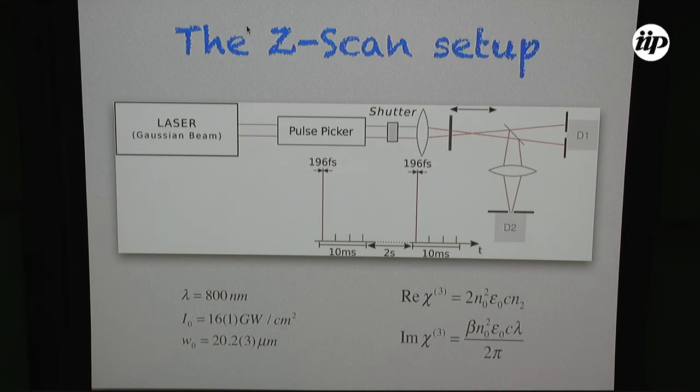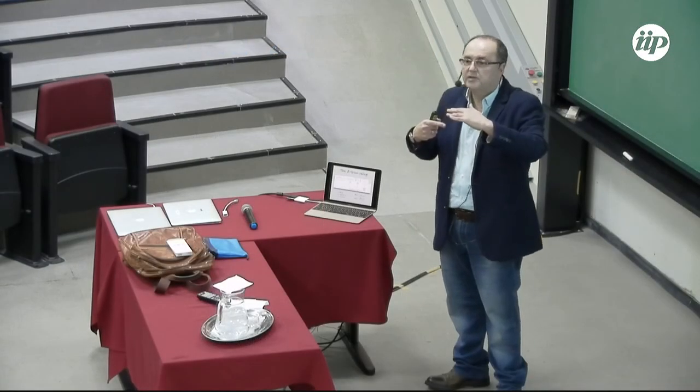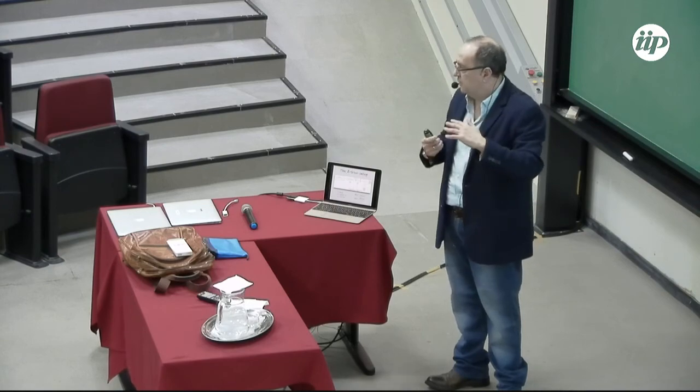You may ask, for example, why do you put this shutter here and you don't work with these small pulses from 0 to about 2 seconds? The response is that if you take into account these small amplitude peaks and sum them over 2 seconds, you will have enough energy to increase the sample temperature and give you a thermal effect response, which is not an electronic response.